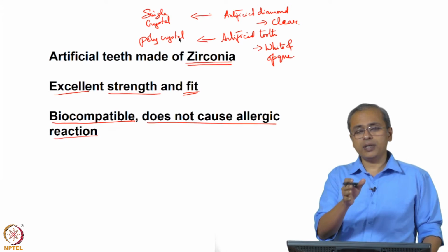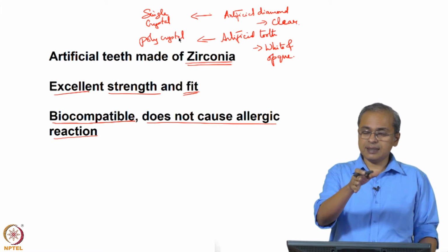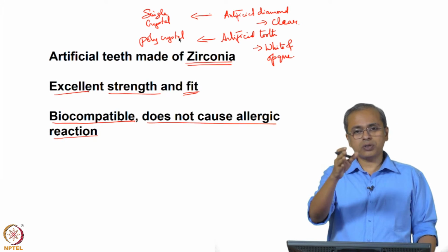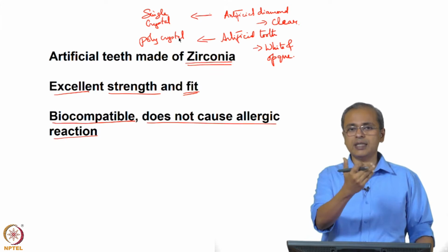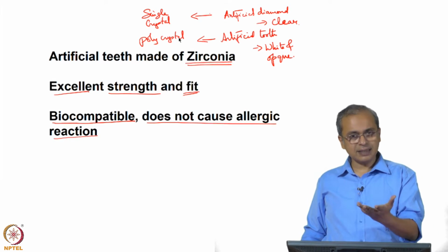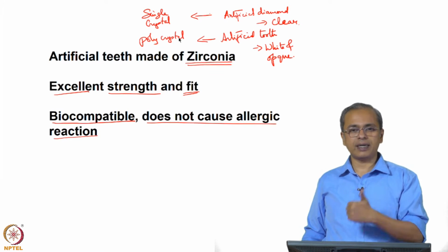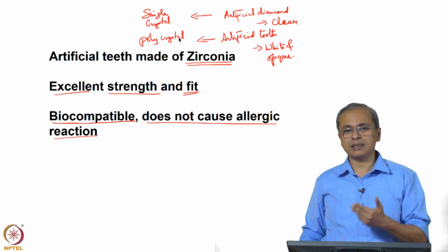And because it is a polycrystal with a fine crystallite size, the light that enters this system undergoes a lot of different reflections due to the boundaries between the different small crystals. As a result, a lot of light is reflected right back, and so even though it is inherently a transparent material, you see it as an opaque material.